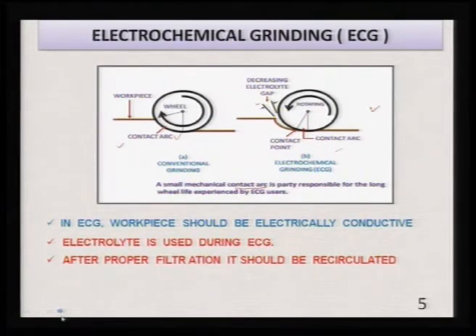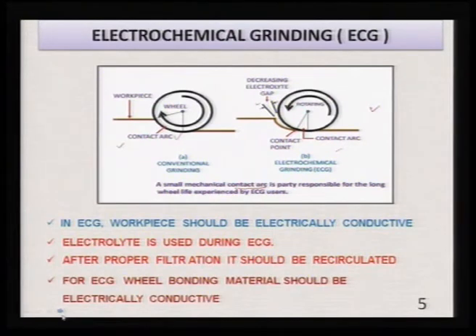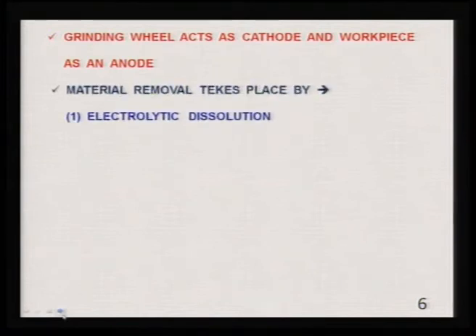After proper filtration, the electrolyte can be reused or recirculated as we do in case of electrochemical machining. For electrochemical grinding, the wheel bonding material should be electrically conductive, as I have just mentioned that it is made as cathode. So the material should be electrically conductive and it forms a part of the electrical circuit of the electrochemical grinding process. The grinding wheel acts as a cathode and the workpiece acts as an anode. Here it is very similar to electrochemical machining, where the workpiece is made anode and the tool is made cathode. So here the grinding wheel acts as a tool.